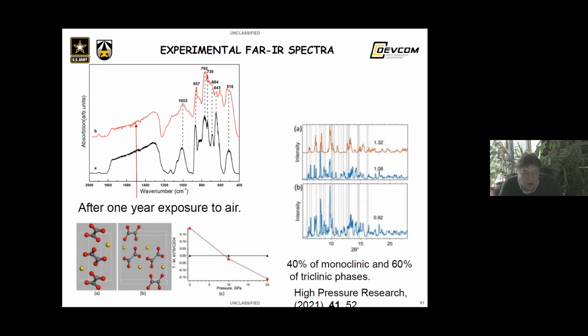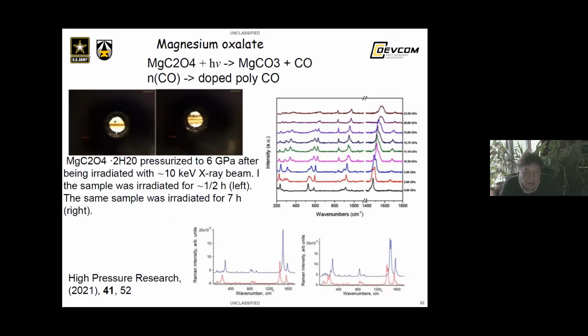We used a method of virtual diffraction developed by Sean Coleman in our group. This method allows us to calculate XRD on high-performance supercomputers with the same accuracy as Mercury from the Cambridge Structural Database. The method might be important for structure search because it allows us to calculate on-the-fly XRD for newly predicted structures and compare with a desirable peak position. The same reaction as for strontium oxalate is possible for magnesium oxalate. Michael Pravica and his students obtained poly-CO doped with magnesium, as might be seen from the samples. This reddish circle corresponds to the poly-CO. Experimental Raman spectra show signs of phase transition.